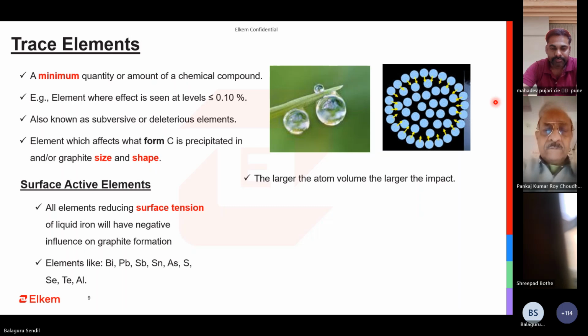So again, the term here is that the larger the atomic volume, the larger the impact. So what do I mean by that? I will explain in the upcoming slides. As we discussed, bismuth, lead, tin, antimony, arsenic, sulfur, selenium, tellurium, aluminum, all these are surface active elements. And we are aware that in foundry, we are dealing with lead, tin, antimony, and sulfur is a very important element. We are having tellurium. That is why when you are having quick cups to determine carbon equivalent, they don't advise you to put it back into your charge mix. So there is a reason to it.